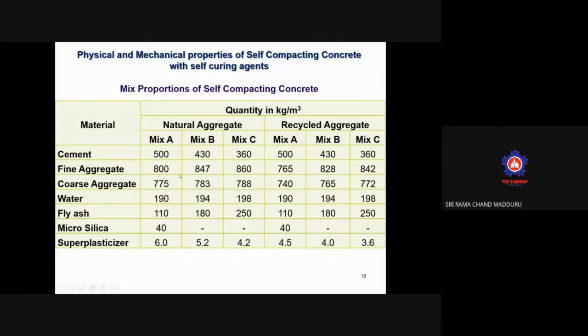And this is the amount of cement content that is added. Yes, you know that as per IS 456, the cement content is 450 kg per meter cube. But in case of mix here, we have taken 500 kg per meter cube to achieve high strength. In case of SCC, we don't have any limitation for the cement content. We have limitation for powder content. And these are the fresh properties that ma'am has explained to you.